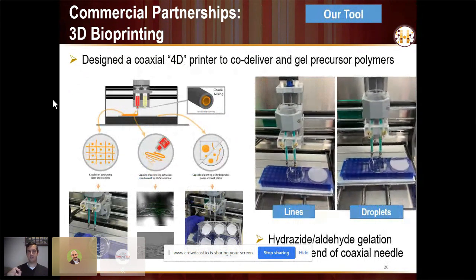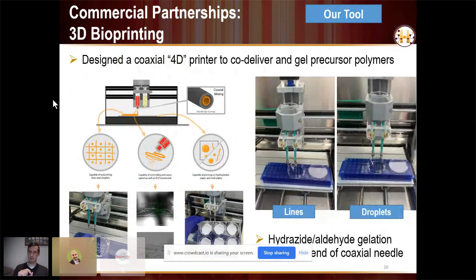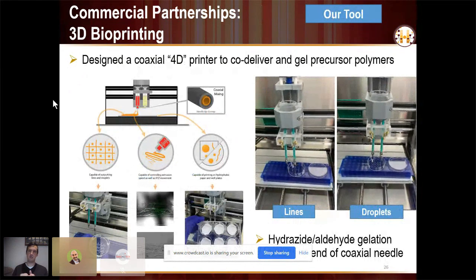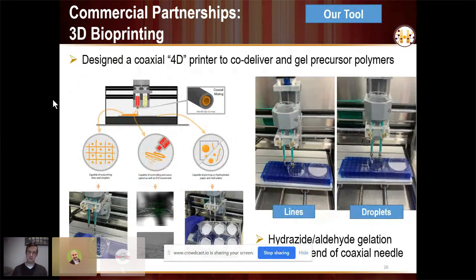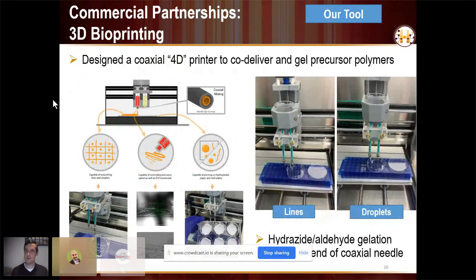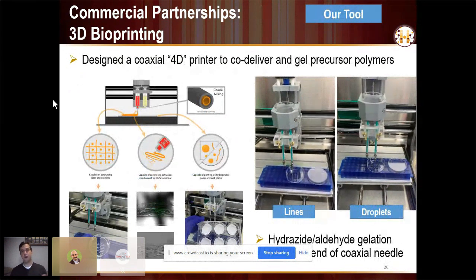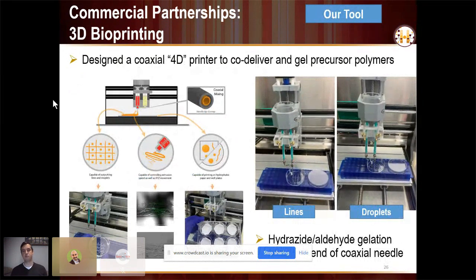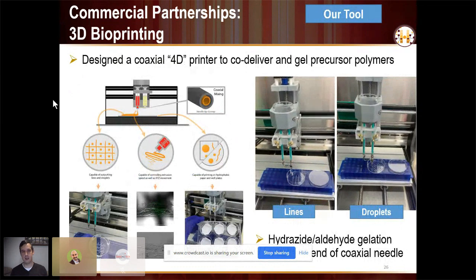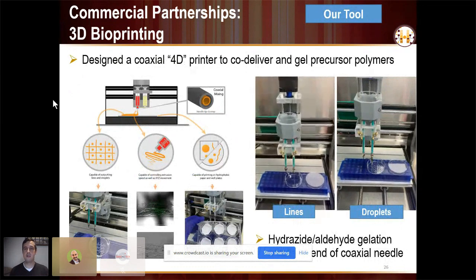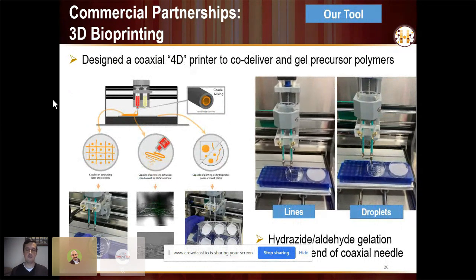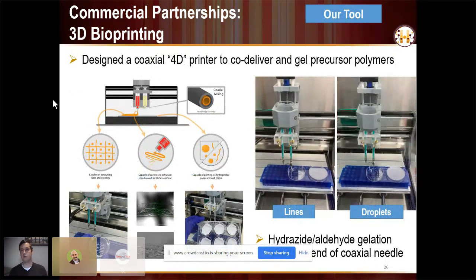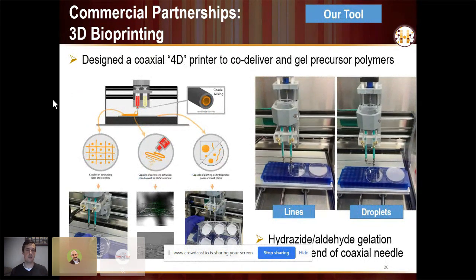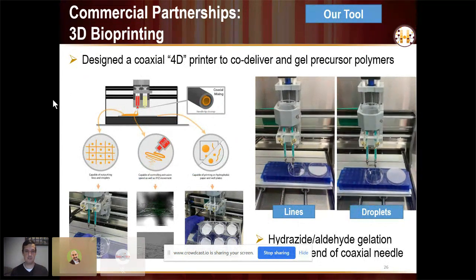At the interface, it isn't completely blunt. There's just a small gap between them. There's a small chance to mix, but it's essentially just a coaxial flow, and thus diffusion of these low molecular weight precursor polymers that is driving mixing in this case. But in this case, we can actually print hydrogels fairly effectively. You see in the videos, we're printing lines, droplets. We create combinations thereof to create some interesting grids.